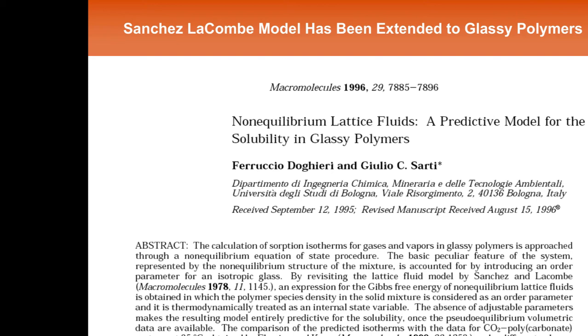You can expect that if those penetrants were closer to one another in their molecular properties, so maybe rather than methane and butane, we would take ethane and propane, or butane and isobutane, things that are closer together in condensability, then you could see that each penetrant influences the other. But in this case, the methane is just not condensable enough to get in the way of the butane. And I haven't shown you yet, but this has profound effects on the transport properties.